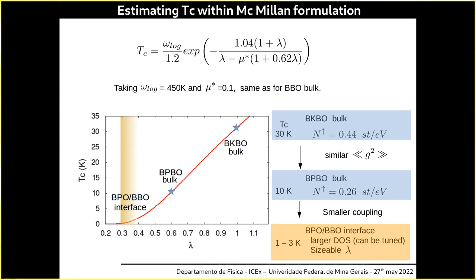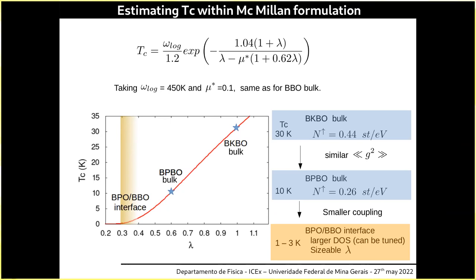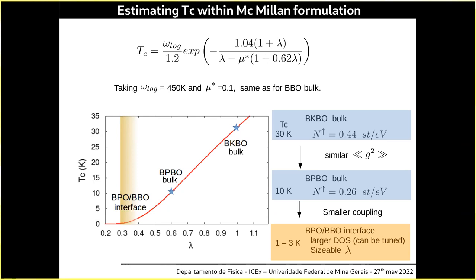In bulk, the crystal structure is monoclinic, but in low dimensions there are defects. Even the resistivity and transport properties are not very clearly understood in thin films. I think it has to do with defects. That's why I'm surprised that with the monoclinic structure, the calculation worked so well.